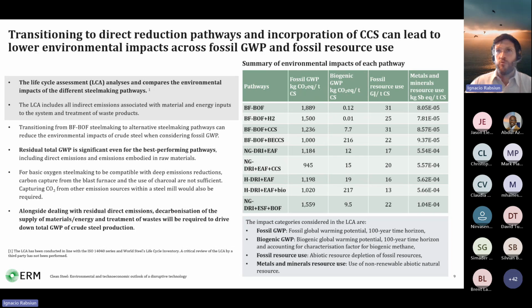It also reveals that even with the most aggressive decarbonization pathways, the residual emissions, the ones that you can see in the fossil global warming potential column, are still very high. So dealing with all those residual direct emissions and indirect emissions, and that means emissions from the captive lime kiln, but also emissions from electricity, emissions from hydrogen procurement, the treatment of waste, all those will be essential to drive down the total global warming potential of crude steel production. Working just on your direct emissions is not enough, and more is needed.